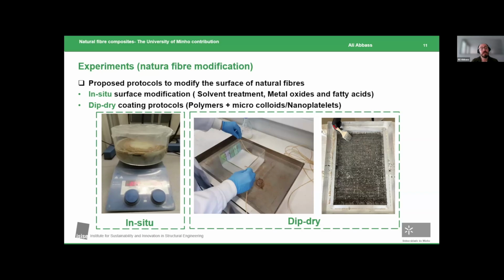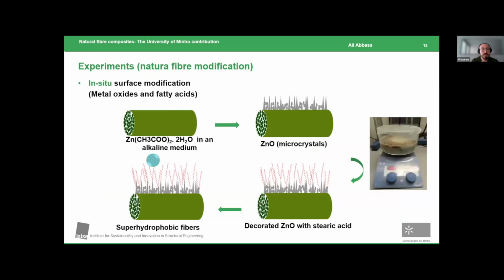The second protocol is dip dry. This is very common, and this is very easy and friendly, and we're targeting civil engineers, so this is very user friendly for civil and structural designers. So in this case, you pre-prepare the coating in a master batch. So you prepare the formulation separately. Then you cast it on the fibers, as you can see here, by dip, dry, brush, spray, etc. Then you heat treat the fibers, the coated fibers, and you have your coated system ready.